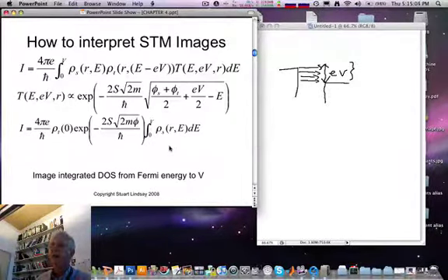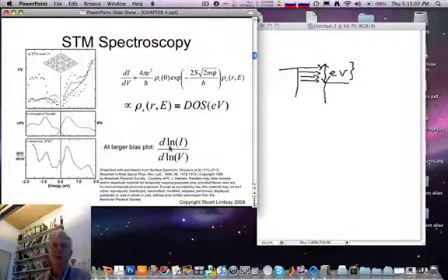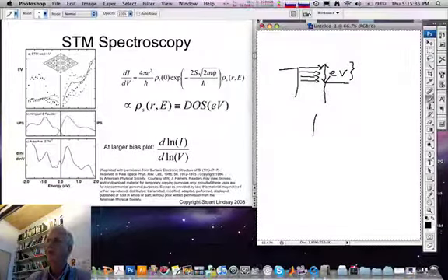This then leads naturally to an application of scanning tunneling microscopy at higher biases, which is a way of measuring the density of electronic states around the so-called Fermi level, which is the highest occupied electronic state in a metal electrode, and we'll discuss that more in chapter 5. So the density of states can be measured simply by looking at current voltage curves versus bias.